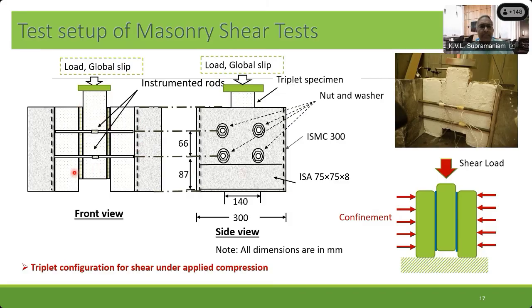What we did, which is a little interesting, is we did a modified setup where we were able to apply confinement on the brick. We had a setup where we put channel sections on the sides, and by tightening the rods, which were instrumented, so we could actually measure the amount of stress we are applying, we could subject this triplet arrangement to a confinement stress and then do a triplet shear test.